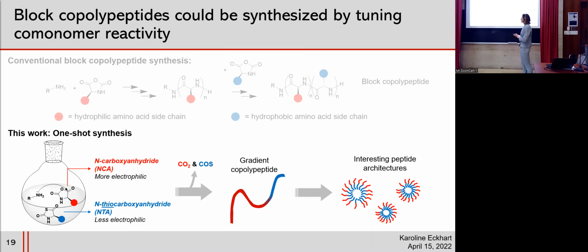So we proposed creating a one-shot synthesis by combining an N-carboxyanhydride with an N-thiocarboxyanhydride monomer, each with a different amino acid side chain. An N-thiocarboxyanhydride is like the cousin of an NCA. It has a sulfur as the pendant atom in the anhydride rather than an oxygen. And this makes it less electrophilic and have higher stability and lower reactivity. So we theorized that by combining these two monomers in one shot, we would get selective propagation of the NCA at the beginning of the reaction. And then once the NCA was consumed, we would get propagation of the NTA.